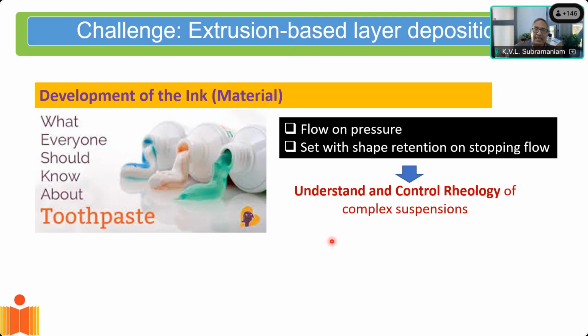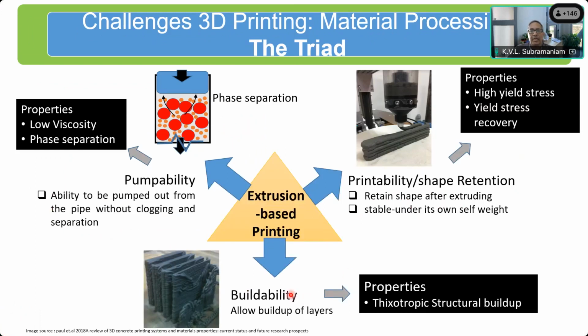In addition to this, I have another requirement that is called buildability. So what are the requirements of concrete that I need to address? Concrete has to be pumpable, it should be printable, and it should keep its shape. So up to this point, the pumpability and the shape retention, it has to behave like toothpaste that I was talking about. But there's an additional requirement. The additional requirement is called buildability. So you can imagine that suppose I extrude or push out one layer of toothpaste, and I start adding more layers of toothpaste on top of it. The bottommost layer should be able to withstand the stress coming on it from the additional layers, and it should not start spreading, because if it starts spreading, the geometric shape gets distorted.